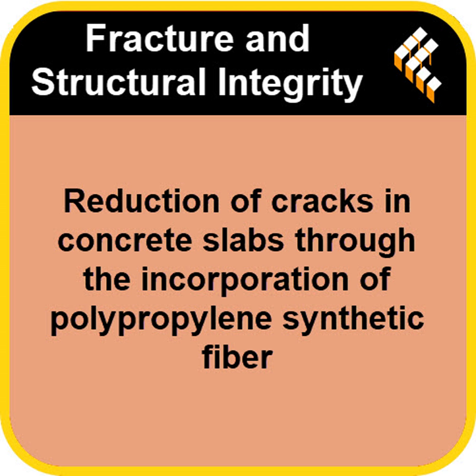So the fiber is what? Holding the water in? Essentially, yes. It's slowing down the drying process. And that had a direct effect on the cracks. At just 2.5 hours, they saw a 71% reduction in crack length. 71%. And a 50% reduction in the number of cracks. Even the crack width was down by almost 13%.